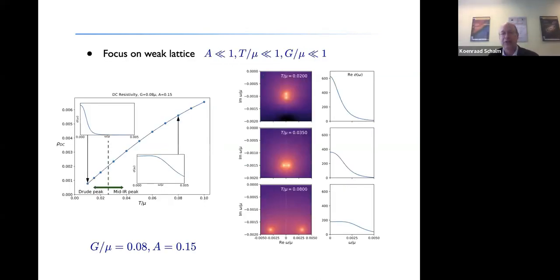And now we can understand actually what happened in this weak lattice example that I gave you. Here again, I have this very robust linear DC-resistivity, where I start with this Drude pole, which is actually not a single pole. It's dominated by 2 parts. This is the ordinary Drude pole, which has this sum of 2 relaxation rates that you can also get from the memory matrix. And this lower pole is the Umklapped charge diffusion pole, that is roughly speaking at the value of the charge diffusion constant times the lattice momentum squared. But they're both on the imaginary axis.